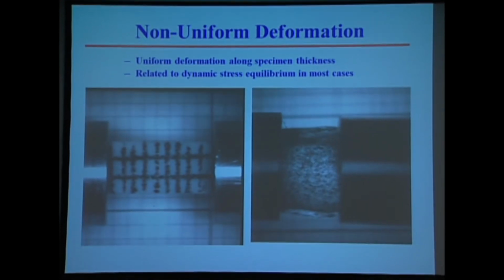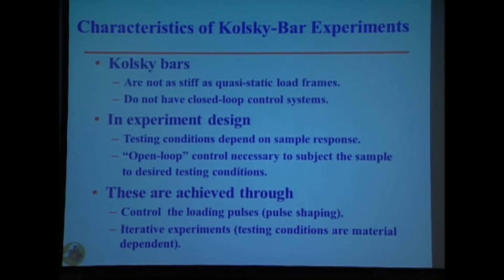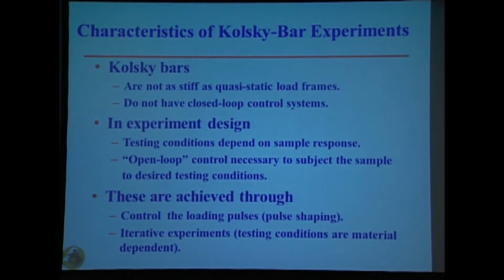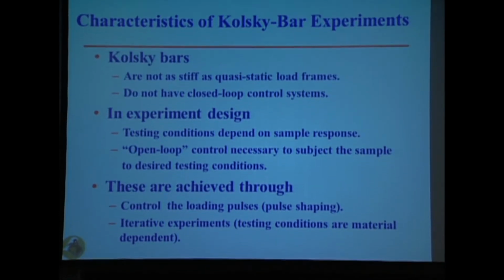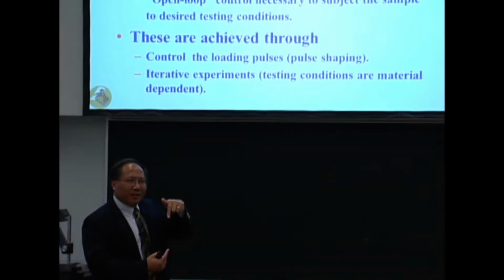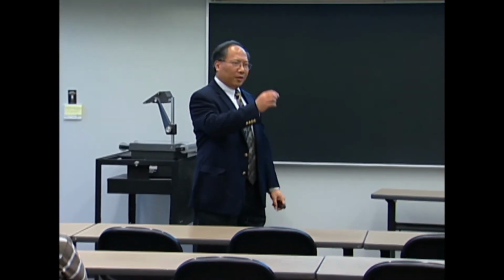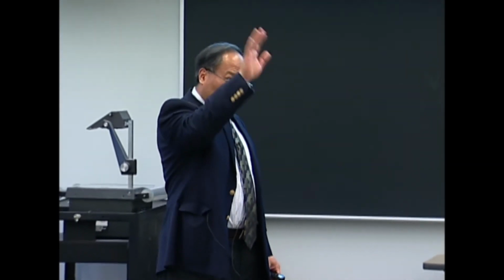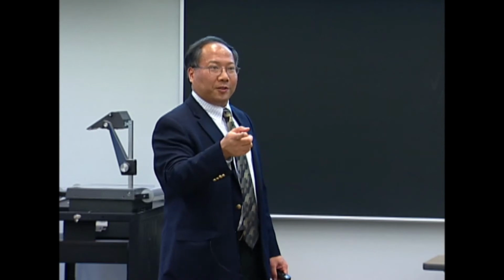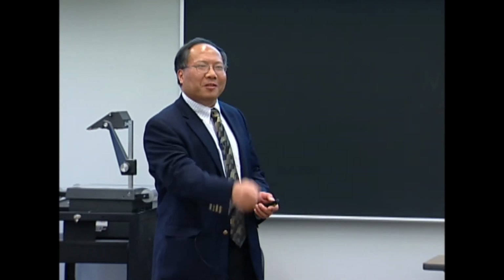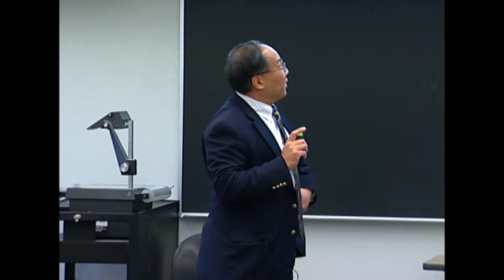So what do we do? You need to look back at the tools we have. We have two skinny rods that sandwich the sample. These rods are much less stiff compared to your static material testing machine. So the sample response to your loading is an integral part of the experimental design. In a static machine, you set the machine, you put in a piece of rubber or a piece of glass, and the machine will run the same way. It has its own closed loop control system. In the high rate impact machine, you hit the same way. If I have a hammer, you hit a piece of rubber or hit a piece of glass. You don't expect the sample to deform the same way. So the experiment has to be designed very carefully.